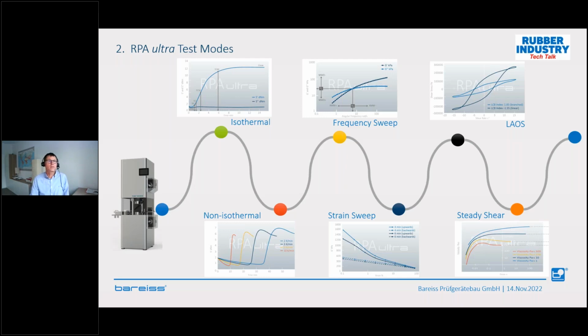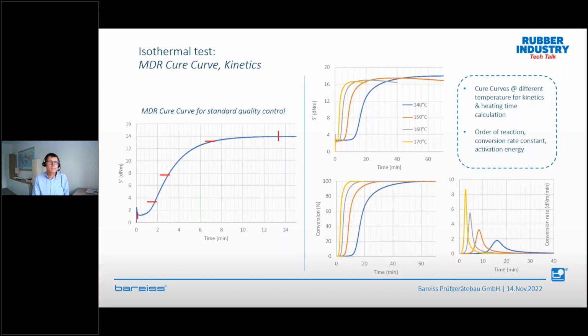So let's start with a typical isothermal test. I think this is what we know. On the left side, you see a typical cure curve. The red lines are the typical gates, the tolerance limits for minimum, maximum, TC10, TC50, TC90. This is what we need for standard quality control, which is very important. And for sure, the RPA Ultra can perform all these tests.